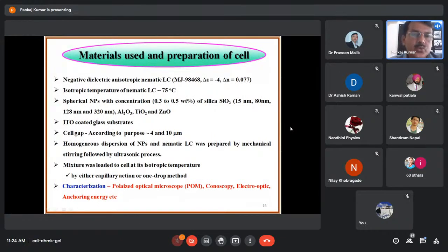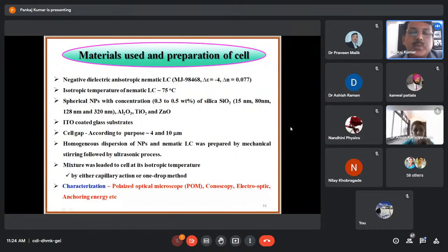So ITO glass substrates have been used. Cell gap according to the purpose. When we want to characterize voltage transmission characteristics, then we have to use 4 micrometer. But when we want to calculate the anchoring energy, etc., then we can change the thickness of the display cell. So 4 micrometer and 10 micrometer we have used. Homogeneous dispersion of nanoparticles and nematic liquid crystal was prepared by mechanical stirring followed by ultrasonic process. The mechanical stirring as well as the ultrasonic process needs proper care and proper handling.